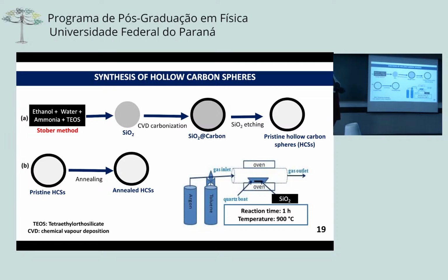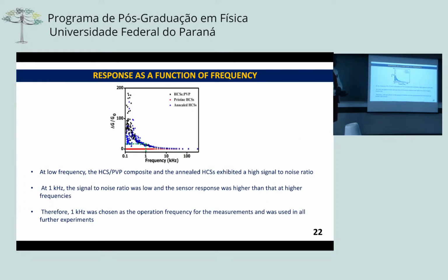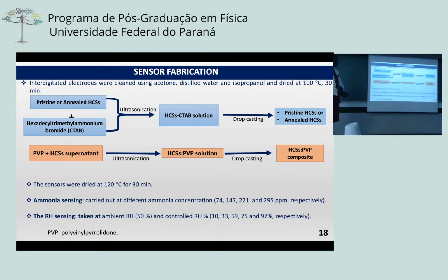To check the effect of annealing, the pristine was heated in air at 300 degrees Celsius to get the annealed hollow carbons. For the sensor fabrication, we used the surfactant-assisted dispersion method, whereby the hollow carbons were mixed with the surfactant, then ultrasonicated and drop casted. For the polymer composite, the same was done, and the sample was drop casted to form the electrode.